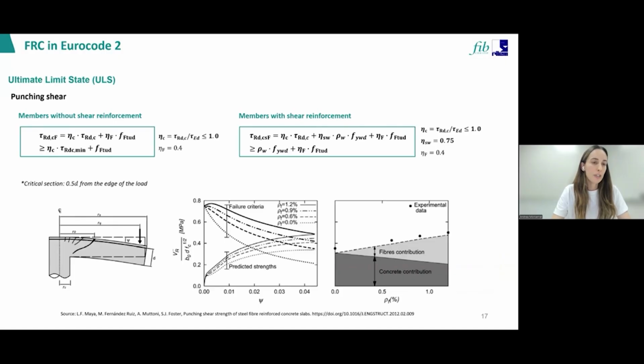significant. If we jump into punching shear, there are several experimental studies that have confirmed the beneficial effect of fibers on both punching shear strength and the deformation capacity of slab column connections. And similar to shear, Annex L incorporates the fiber contribution through this additional resistant term, but in this case, only 40% of this contribution is considered in the formulation through this parameter eta F, which is 0.4 in this case, instead of 1, which was the case of the shear. In addition, the code introduces the interaction parameters to account for the fact that the fiber contribution, as in the previous case, is not fully additive to the concrete or reinforcement contribution.